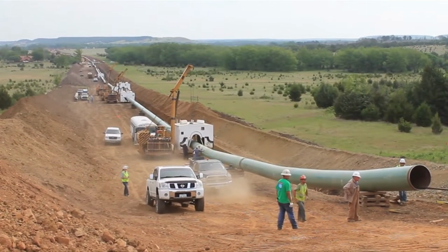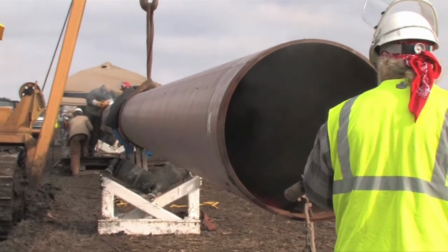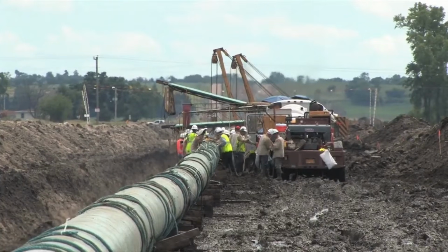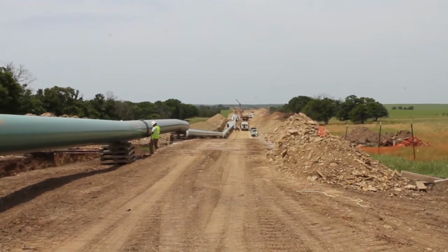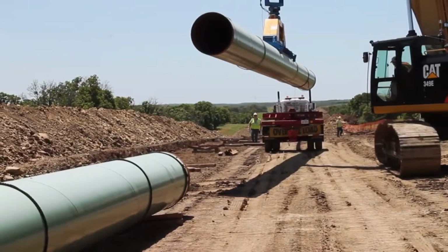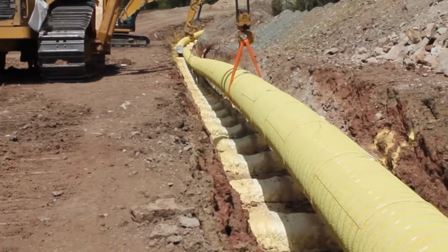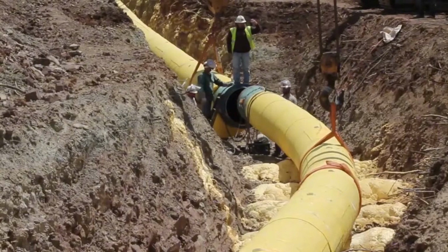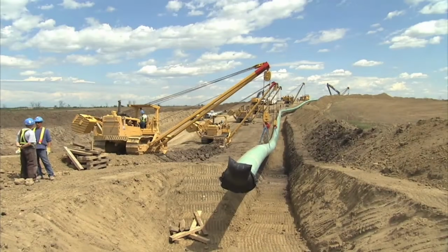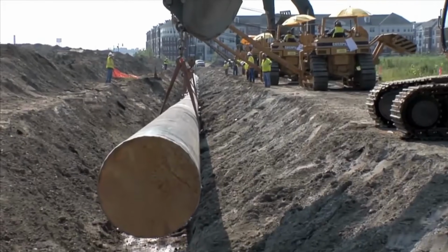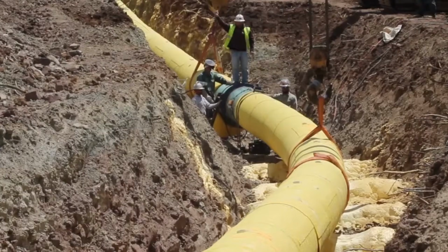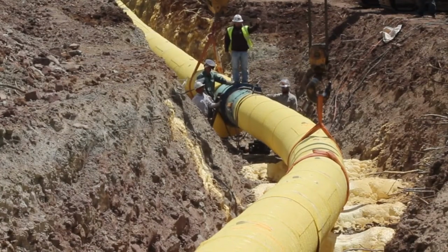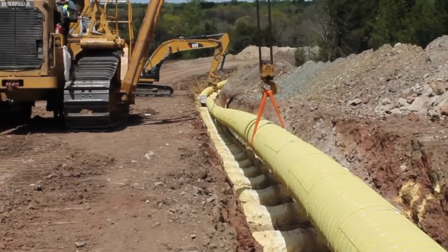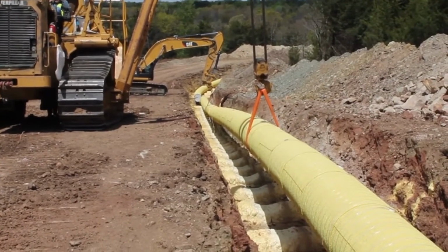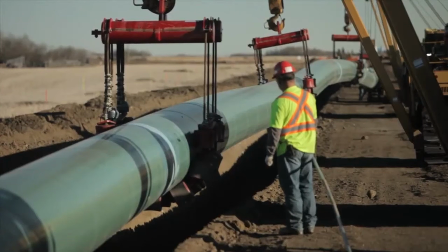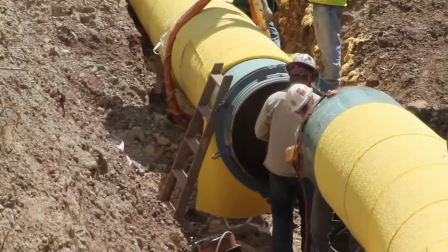Certified welders join sections into runs, several thousand feet long. Every weld inspected visually, then verified by radiographic or ultrasonic testing. Coating gets repaired at every joint before pipe drops in. Side boom tractors lower the string onto sandbag benches. Then the whole run gets hydrostatic pressure tested well above maximum operating pressure and held for hours. The pipe either passes or gets cut out and replaced. Nothing in between. Multiply that discipline by thousands of miles. And that's the invisible skeleton of American energy.